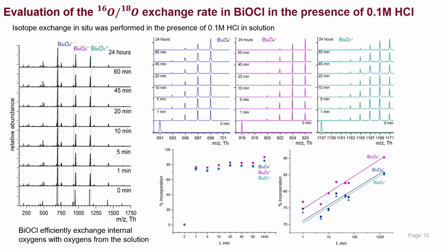And in this change, from the time course perspective, we can detect two phases. In the first minute, there is a strong, fast incorporation of oxygen-18, and the total percent of incorporation is around 75%. After that, there is a gradual increase over the day in our experiments, and the total incorporation rises up to around 90%. And this can be detected from any of the ions presented in the spectrum.